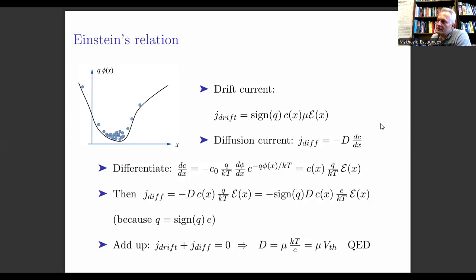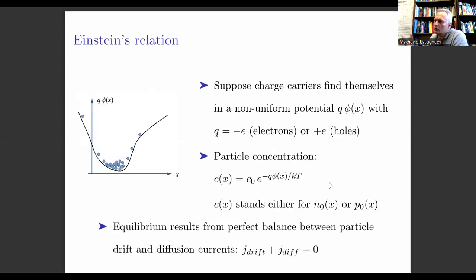In conclusion, I want to say that Einstein's relation relies on classical statistics because we have used Boltzmann's formula for the non-uniform carrier concentration. In the degenerate case, that is when the Fermi energy is close to one of the bands, to the edge of the valence band or the conduction band, Einstein's relation breaks down because it is not a law of nature. It is an approximate formula, used when classical physics is valid. In the more general case, you need to apply Fermi-Dirac statistics rather than Boltzmann statistics.